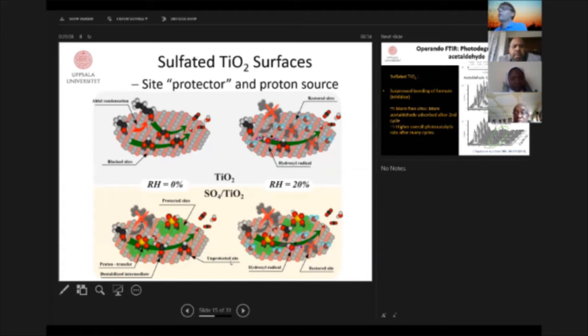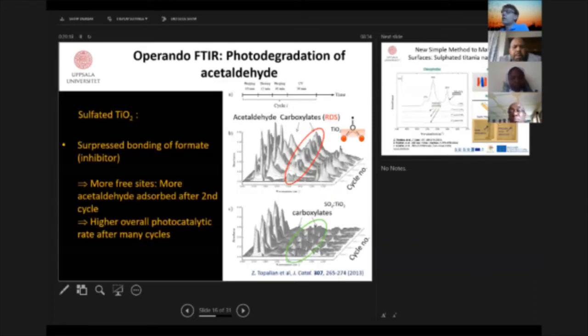Just to exemplify what I said about the Sabatier principle, if you remember, many of these VOC oxidation processes are prone to this deactivation process due to the bonding of these molecules. And this is a 3D graph where we do operando FTIR and show that these build up. And these are the vibrational signatures of these species here. And you don't want them because they build up. And if you add in sulfated titanium, you can see that these simply don't build up on the surface. And indeed, we have a sustained activity on these catalyst surfaces.